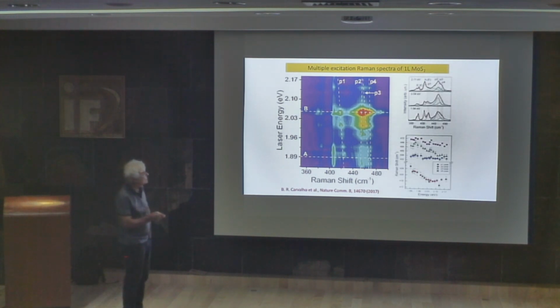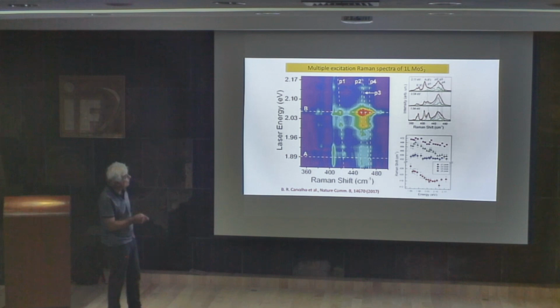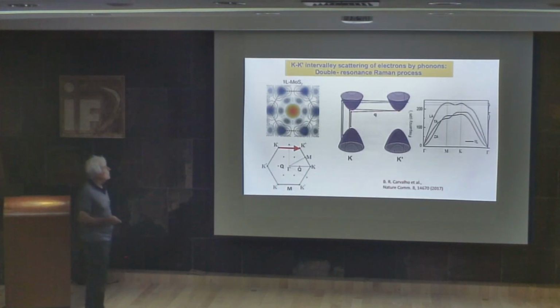Okay, then we can see that in fact this 2LA band is composed of different contributions, and we could fit the data with different contributions. And in this graph here, we have the frequency of the peaks as a function of the laser energy, and you can see that we have this kind of dispersive peaks. Then it's a new kind of phenomenon. Then that was explained, as in the case of graphene, by this intervalley process.